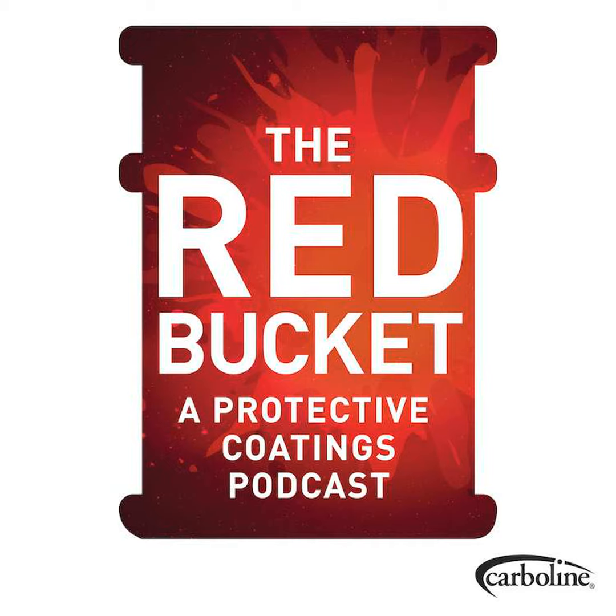I think that does a really good job of summarizing up water and MVT and the problems that you're going to have there. So when we're inspecting concrete, there's also more to it than that. Sometimes you can visually see when you walk in, not new concrete at this point, but maybe we're coating aged concrete, you can walk in and visually see some contaminants and things like that. Well, we said earlier that typically concrete will have around 12 to 13 pH freshly poured. Well, if you come across the surface and the pH is below 9, I'd have a concern. If you come across areas where the pH is above a 12, I'd get really concerned, because that means they've probably been dumping chemicals that are high alkaline in nature. The acid side of it goes after the cement portion. Yep. Okay. And they'll neutralize each other.